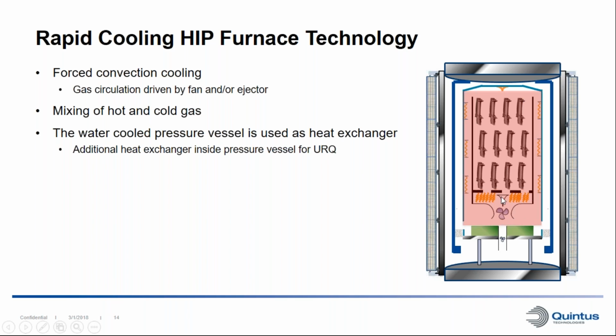So what we do is that we push in cold gas from outside the furnace to inside the furnace, where it cools the part, and the hot gas inside the furnace will be pushed outside, and this gas will actually be cooled down on the pressure vessel walls. And since the pressure vessel is water cooled, we can actually use it as a heat exchanger. In the case of URQ, when we want to achieve the very highest cooling rate, we actually add an additional heat exchanger into the pressure vessel.